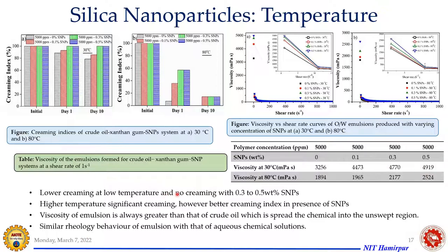So low creaming at low temperature and no creaming with 0.3 to 0.5% nanoparticle concentration, as we have seen here. At high temperature, significant creaming. Okay. However, better creaming index in the presence of nanoparticles. So nanoparticles give a better result compared to their absence. And the viscosity of the emulsion is always greater than that of crude oil. So that's why we maintain a favorable mobility ratio, which pushes the oil from the rock surface to the production platform. So the rheological property is what we have seen in this case.